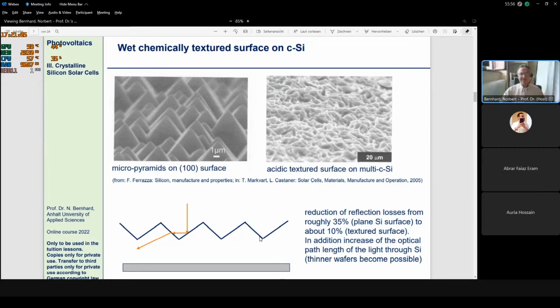And the side faces of these pyramids, they are 111 surfaces. And you see these micropyramids are created just by the fact that an etchant is chosen, which etches the 111 surface roughly by 2 orders of magnitude slower than the 100 surface. And therefore, of course, at the end, only 111 surfaces remain. And these 111 surfaces, they form these faces of the pyramid. This, of course, does not work with multicrystalline silicon, because the prerequisite for that is that we have a 100 surface. In multicrystalline material, we have just a random distribution of surfaces, every neighboring crystal grain has a different surface. And therefore, here we use an acidic etch. And in the acidic etch, we get just this random structure here.